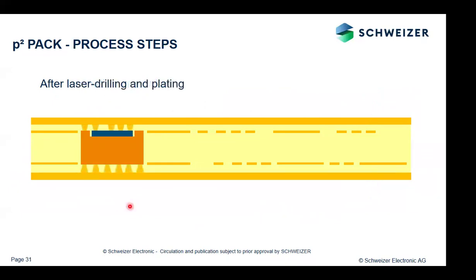So after this lamination process, you need to create openings by a laser drilling process, which are afterwards running through an electroplating process where you fill all the blind vias. What you can see here is the contact to the drain, to the gate, and to the sources of the contact. And as you do the laser drilling and plating also from the backside, you can create a very low thermal resistance by adding these copper-filled microvias on the backside of the standard cell. So the power dissipation is going here to this layer, and you still have a little bit of heat spreading.